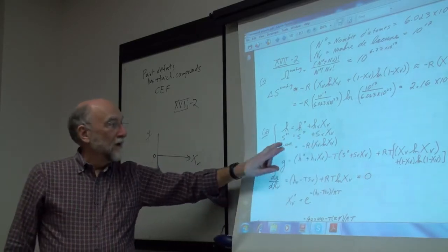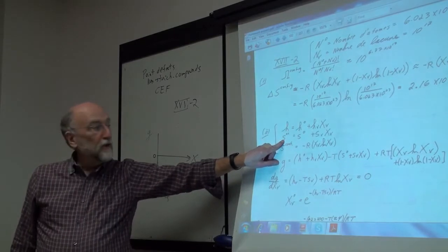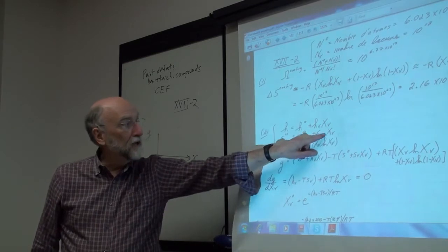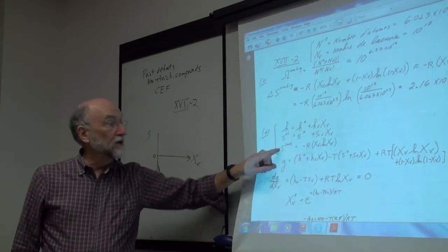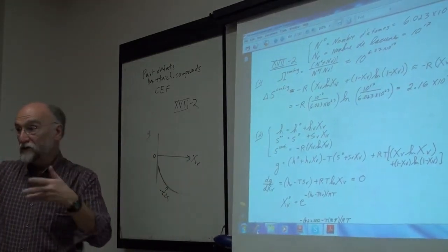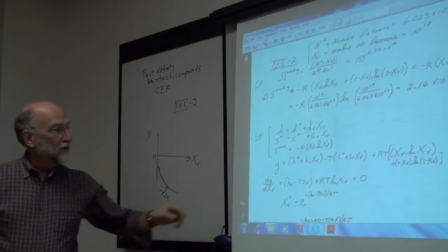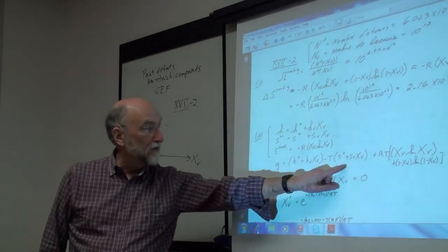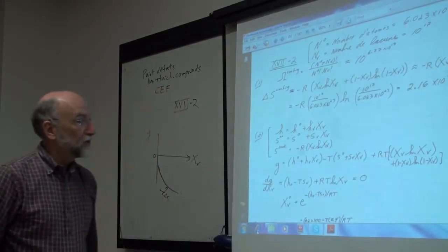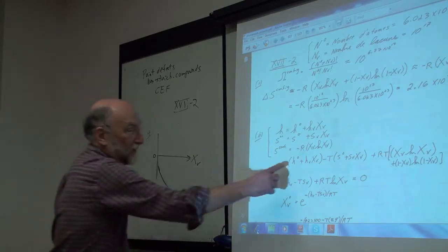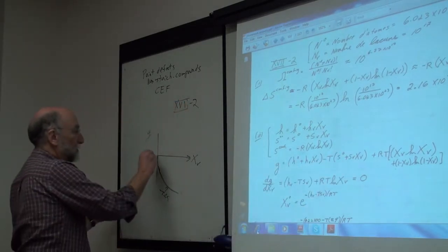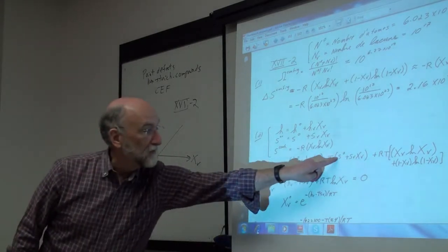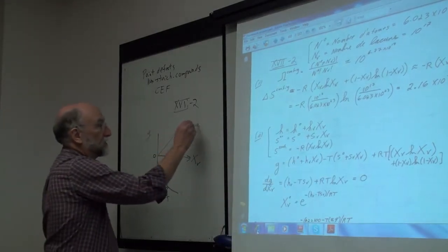This will be your non-configurational entropy, which is S0 plus SV times XV. This is just a temperature dependence. This is a similar non-configurational entropy around a vacancy. The vibrations change. So your first term here, the Gibbs energy of forming the vacancy, is the enthalpy of forming the vacancies plus the configurational entropy. The enthalpy plus the non-configurational entropy is a positive line like this. This is positive at any given temperature. This is T constant.